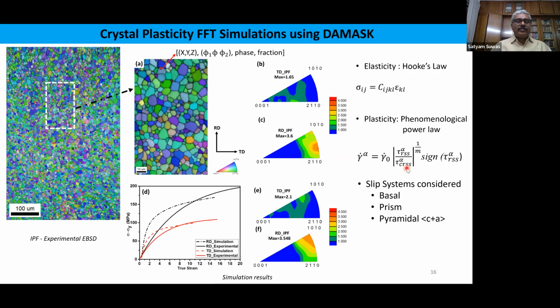The prediction of strength, or strength anisotropy, was carried out by the Düsseldorf-originated software DAMASK, which almost everyone uses now. And particularly this part of the experimental scan from EBSD was used. This is enlarged here. And then we have used this simple phenomenological power law, considering all three types of slip systems.